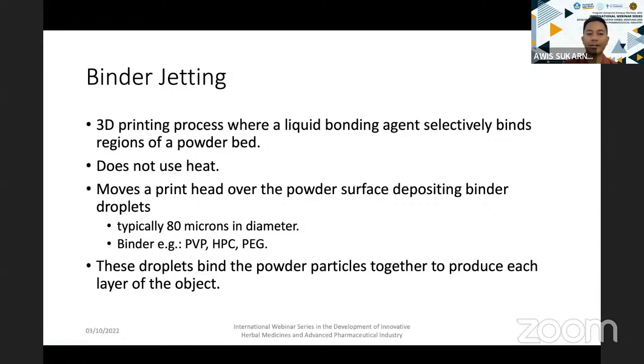In terms of the binder, normally you will use the normal binders that you use when making tablets. The common one is polyvinyl pyrrolidone, PVP, and you can use HPC and PEG as well. HPC is hydroxypropyl cellulose, and PEG is polyethylene glycol. Normally they use a water soluble binder because it's easier to dissolve. And like I said, the droplets will bind the powder together and create the 3D object that you just designed.